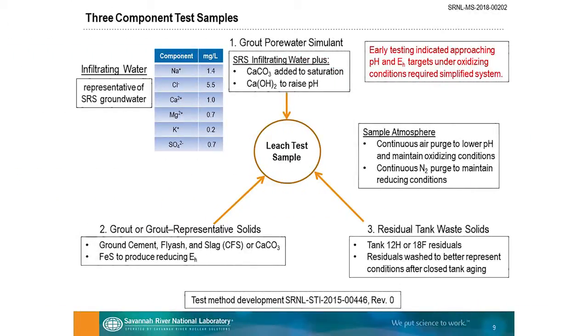Through a series of tests that were done initially with simulants, we came up with a method to test and try to reach those target conditions that I showed you in some of the early slides. And in the end, it ended up being a 3-component sample that we made for each condition of interest. The first component is a grout pore water simulant that's composed of infiltrating water. It's a simulant of SRS groundwater of that composition, plus calcium carbonate added to saturation and calcium hydroxide utilized to adjust the pH as needed. So that's the first component.